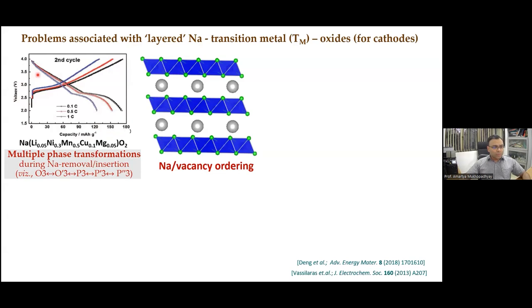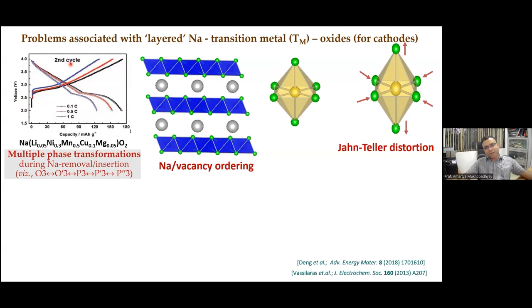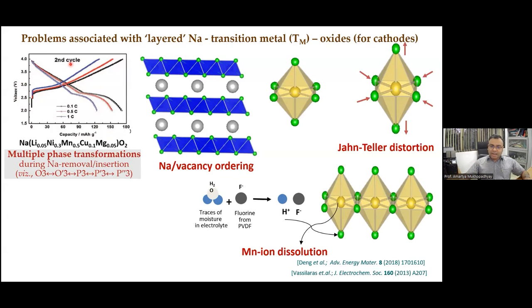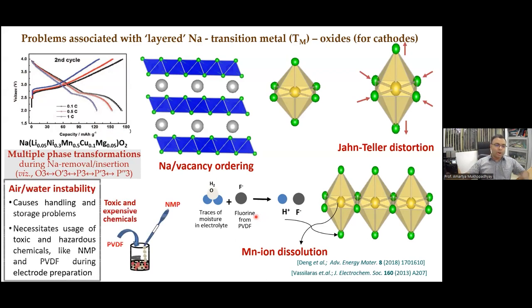With multiple substitutions, one can reduce the number of transformations and render it more stable. The second is Jahn-Teller distortion, if there is a Jahn-Teller active ion present. The third is the transition metal dissolution, if some ions which are susceptible to dissolution are present. And the fourth, and very important, is the air-water instability.